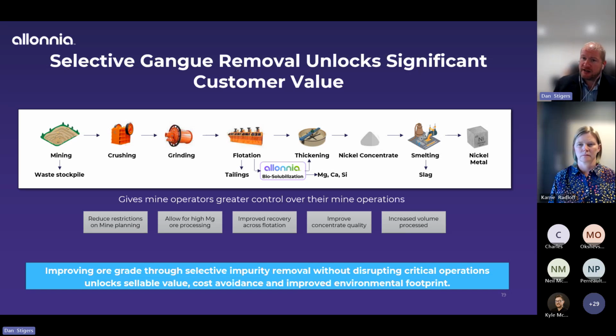And if you're bottlenecked at your smelter, you now would be able to push further production because that slag can flow out much easier. And as we see in this flow sheet, not only do we have the benefit impact in this simple biohydrometallurgical leach step to increase the grade going through the process, it also provides us a unique opportunity to generate an aqueous stream of these impurities to do something with, as Karrie was pointing out, be it CO2 sequestration or utilization for any other industrial process that might be viable locally where the processing plant is.